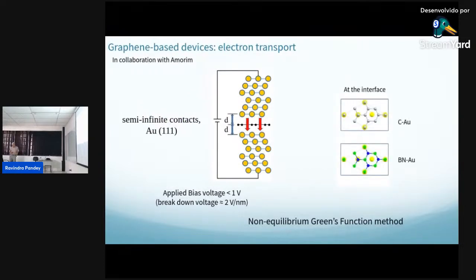So what we have done again, with Rodrigo's collaboration, is pick up the interface, the graphene monolayer, bilayer, or trilayer, and we applied this left contact and right contact. Again, we are looking at a bias of less than 1 volt, because you have to be very, very careful. We are applying this bias at a very, very short distance, so the breakdown voltage of the field is very, very high in that sense.